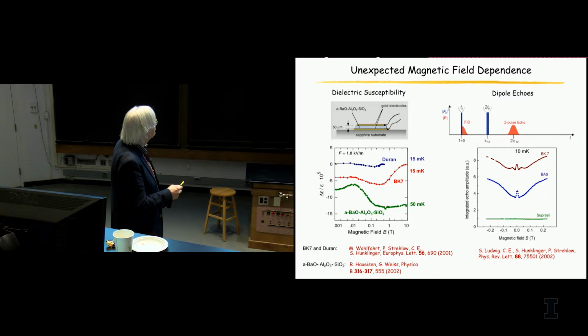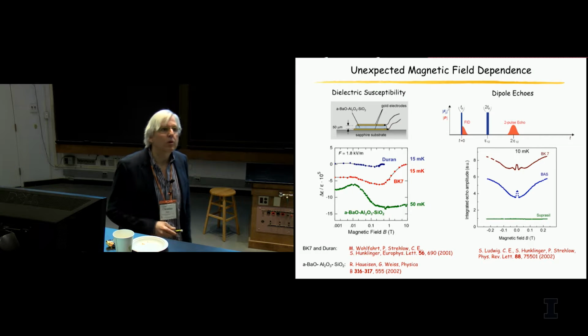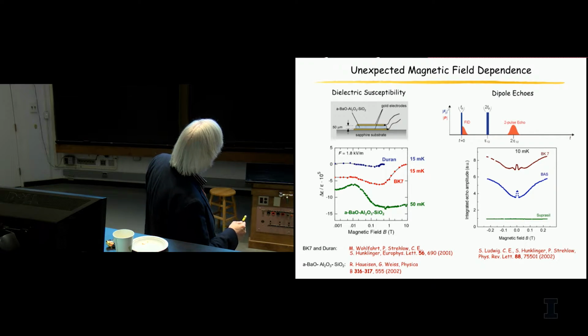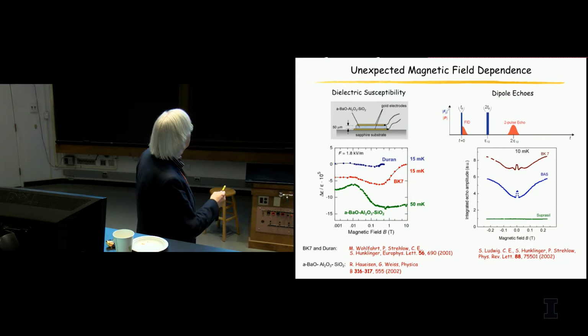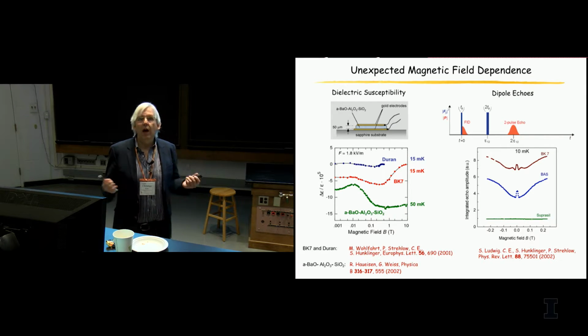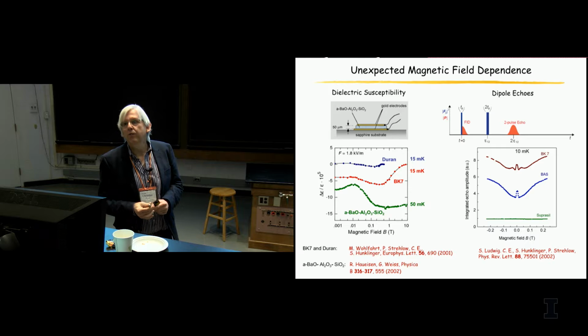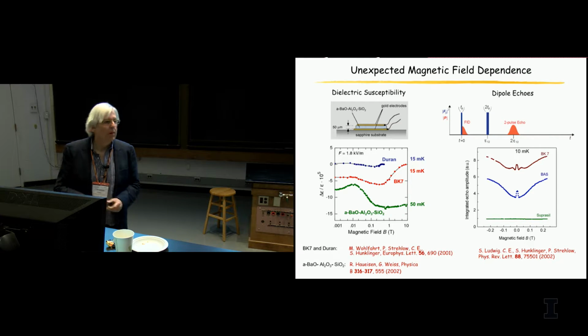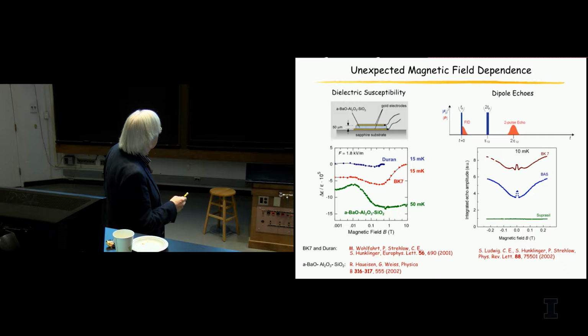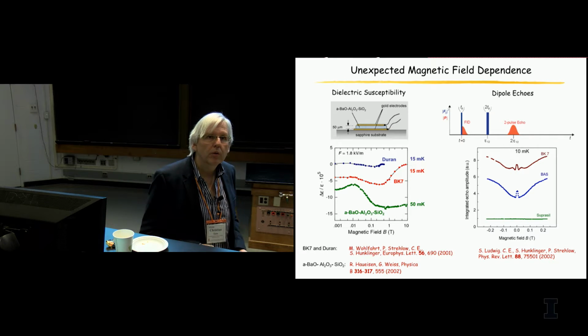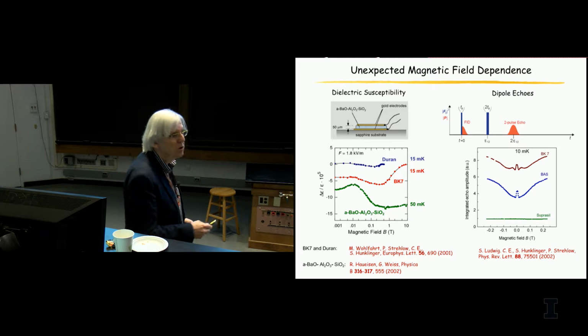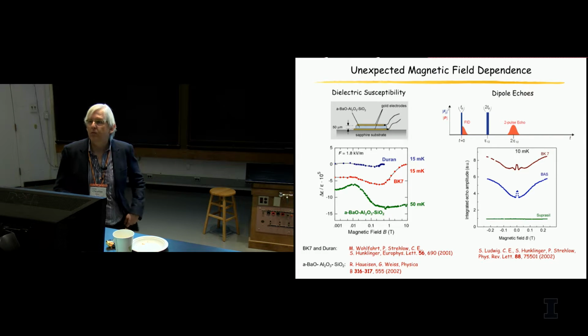For this optical glass here, BK7, you see again a non-monotonic behavior of the echo amplitude. It was very strange because at the highest fields, the coherence, this is what you measure with this kind of echo, was largest. There's no reason why the coherence should increase if you apply a magnetic field. Now, there was another glass, and you see already there are slight differences how they behave. But then when we looked at SiO2, there was nothing. There was an echo, but there was no magnetic field dependence. That's what we expected in the first place.